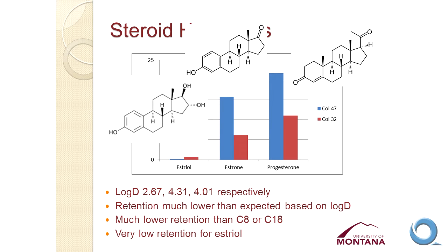We looked at a series of steroid hormones, which are fairly hydrophobic, with hydrophobicity similar to that of some of the more hydrophobic PAHs that we looked at. We anticipated seeing very strong retention of these compounds and that perhaps this would be an interesting application of these materials. And in fact, we did see retention, but we saw very weak retention relative to what we had expected, and also much, much weaker than C8 or C18.